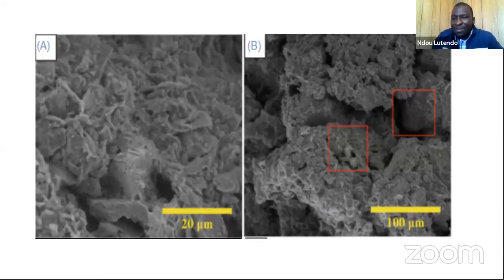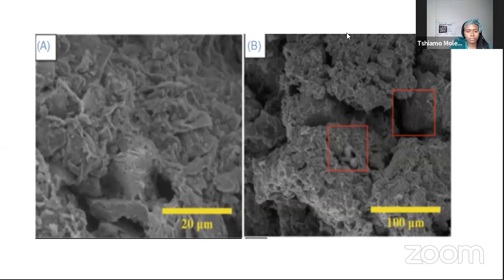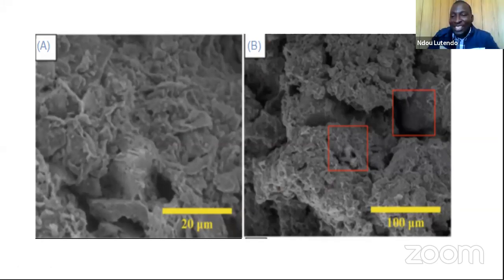Now, you can actually see that this material, they are almost not distinguishable. You cannot actually distinguish a single grain. They're actually covalently bonded. And these are still the tailings materials. So you can actually see that they are bonded at this stage. And that is what we call a geopolymer now. Now, with this bond, the chemistry bond, that's where the mechanical properties come in. If a material is strongly bonded and it's not easy to break through, that means that material has high strength. And hence, this geopolymer technique can actually be used to bring about this green cement, because they're actually strong and they're actually covalently bonded.